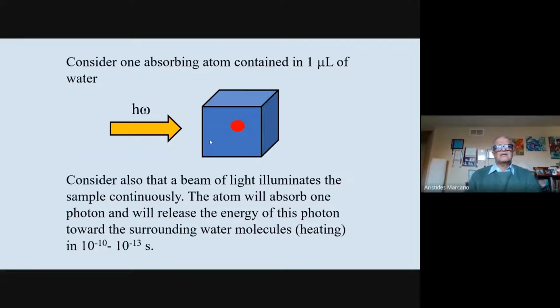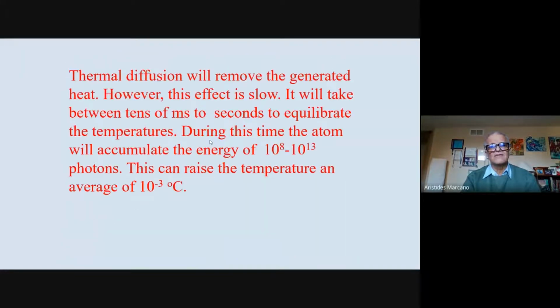You can actually see that that happens very, very fast. It means that that heat will be there, but the heat can move, of course, because of these diffusion effects, thermal diffusion effects. They will remove that heat somehow, but that process is very slow. It takes milliseconds to seconds to equilibrate, to get the temperature equilibrium in this microliter of water. And it's going to take too long to get the equilibrium there.